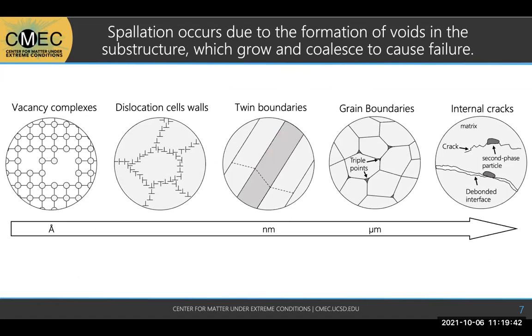So the reason spall occurs is due to the formation of voids in the substructure, which grow and coalesce to cause failure. Generally, in fracture mechanics, failure occurs because material tears itself apart, whether that is from a crack or a void. And so this is really no different, just occurring at higher strain rates. So the formation of voids can occur at a variety of length scales. That's what I'm showing in this image.